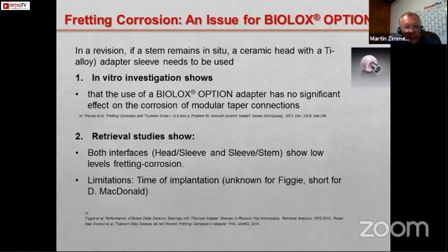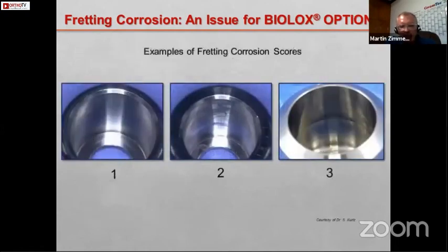There's also a retrieval study going on this aspect and analyzing now both interfaces, because by having a sleeve you have one supplementary interface. You have now an interface between the ball head and the sleeve, and between the sleeve and the stem. And they analyze now the level of fretting corrosion. But they came to the conclusion that in these two only studies that exist up to now about this analysis on the BIOLOX option system, the time of implantation and the number of implants was too short to make a very clear conclusion. But let me show some pictures coming from these retrievals.